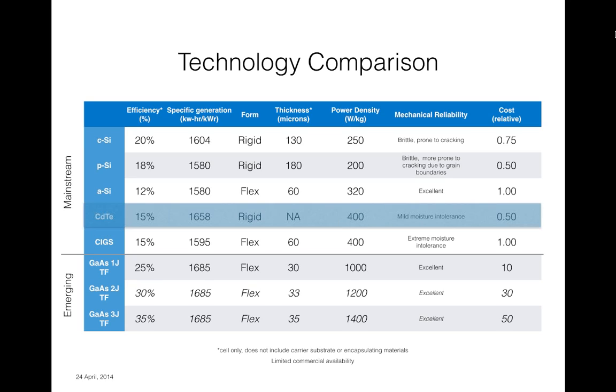So just continuing then, the CIGS material is now coming into the mainstream. Its cost is modestly more expensive ultimately than crystalline silicon. But again, if you can live with the performance that you get for the 400 watts per kilogram and the 60 microns of thickness on a metal foil, and that can be integrated in aircraft, if that produces a meaningful benefit, then this material is a good choice because it's very low cost and it has reasonably good performance in terms of energy collection. However, we find, or at least my experience has been, that you want more energy. 400 watts per kilogram is not enough to get you excited about going to the task of putting it on an aircraft.